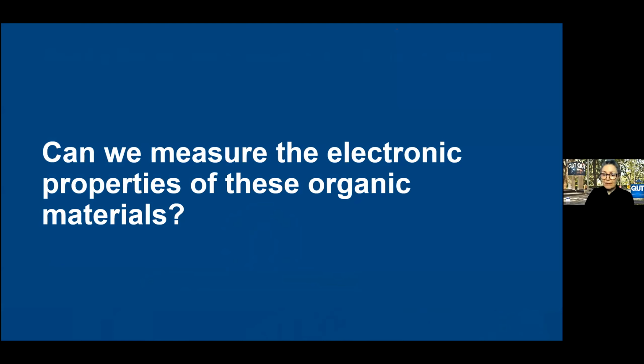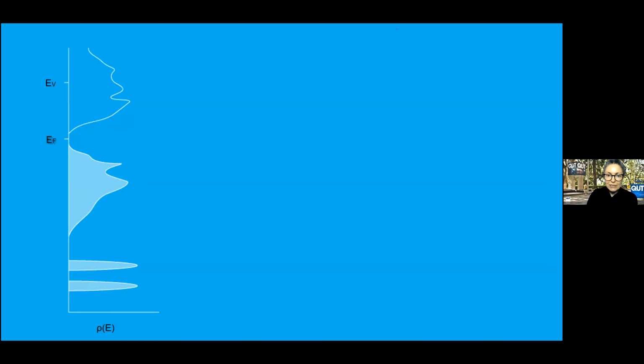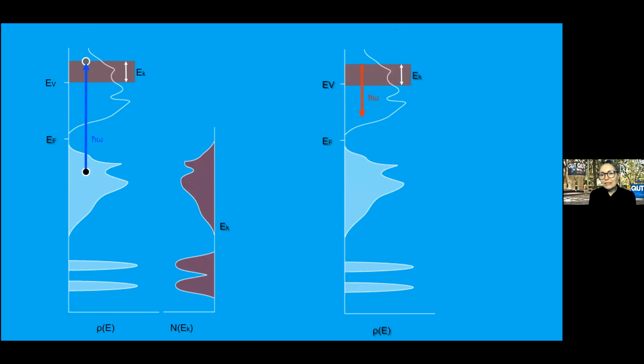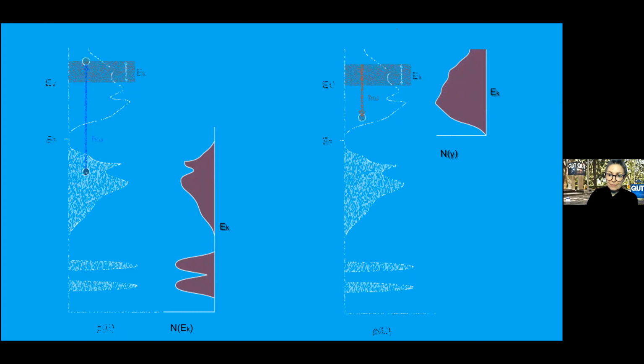So just very quickly before I finish, we are interested in particular in targeting electronic properties in these materials. And we've been measuring that in a conventional way in our system, looking at figuring out what the density of states looks like for these materials. When we're looking at filled states, we do that through ultraviolet photoelectron spectroscopy, just schematically illustrated there for you. That's a photon in, electron out technique where we're able to map the filled states. And of course, we've also been working on the development of an inverse photoemission spectrometer, which is an electron in, photon out technique where we're able to map the unfilled states.